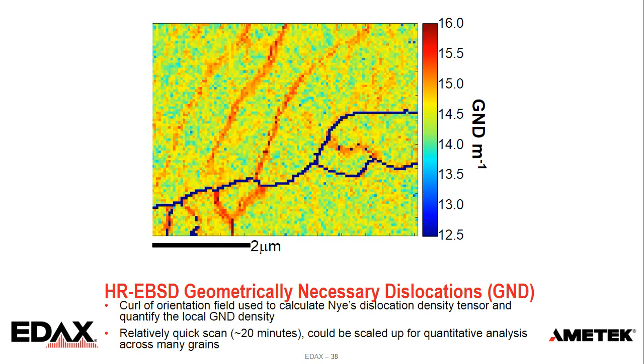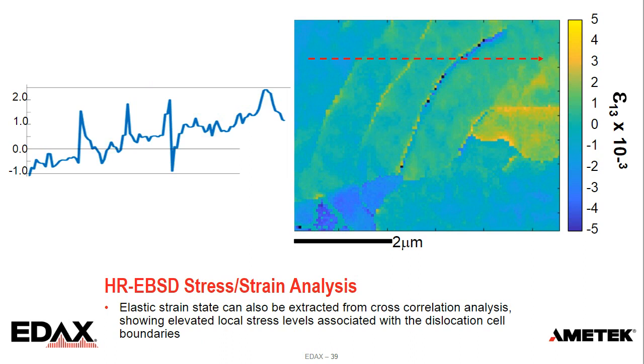And once we have that, we're also able to look at the stress and strain that comes out of that cross-correlation analysis. This shows a profile line going horizontally across some of those cell walls, and we can see the stress state going along that. We see where it can go from a state of compression to tension along those different parts of the dislocation structure. It's relatively new, but it's been around for a while now, more information we can extract from the EBSD patterns.